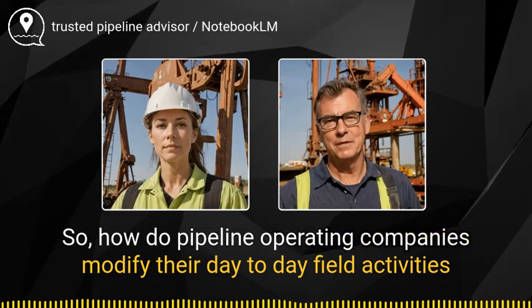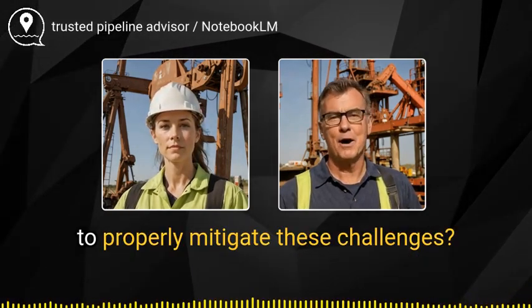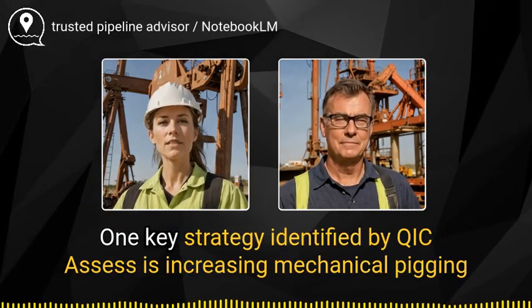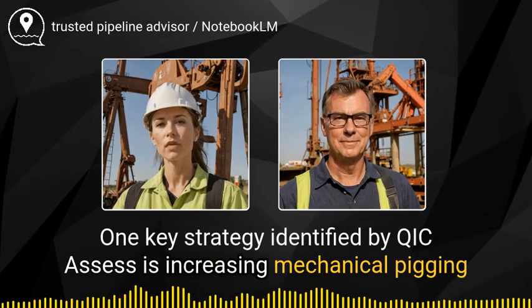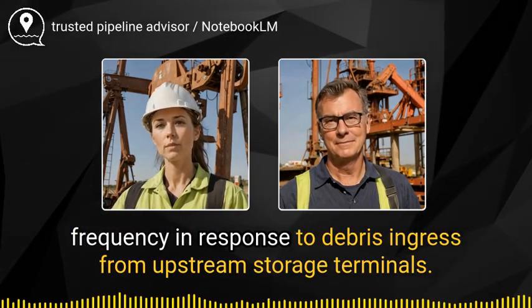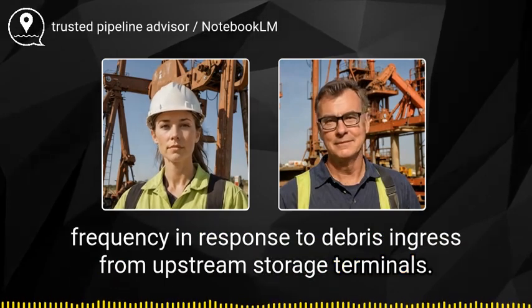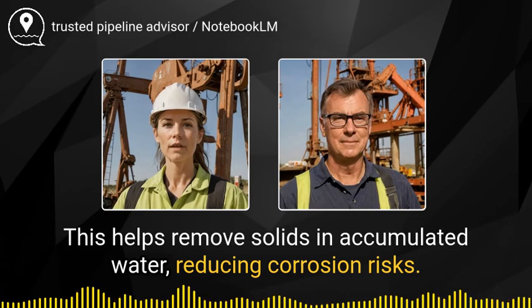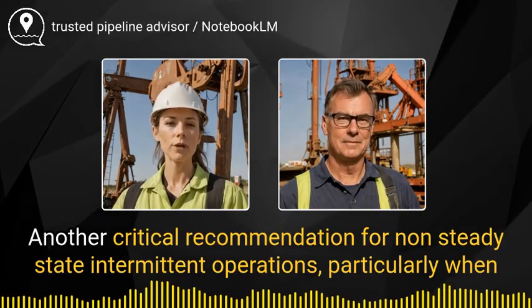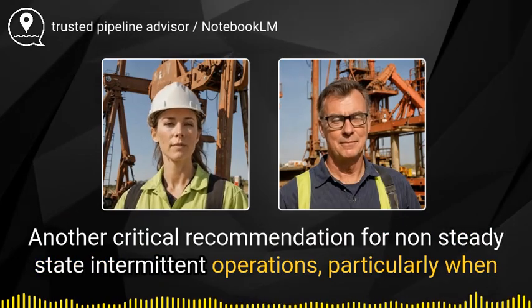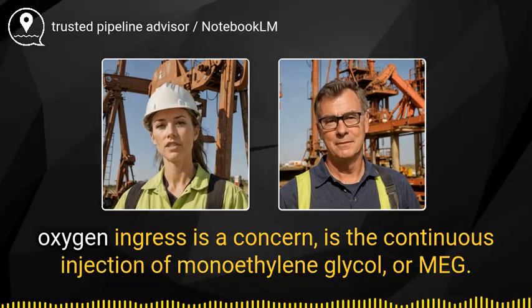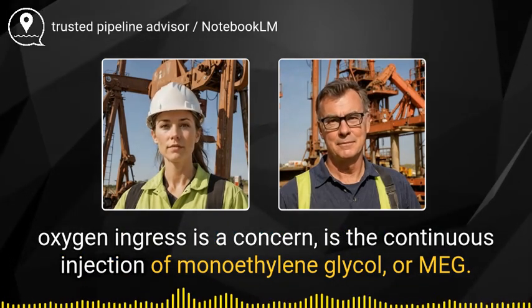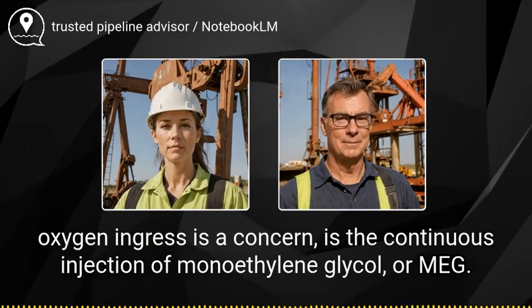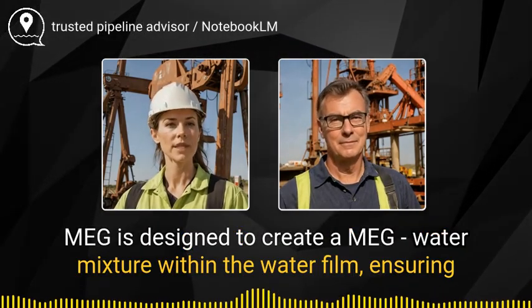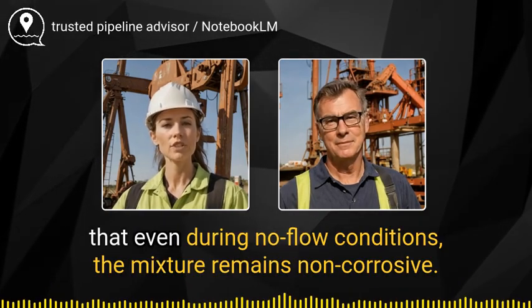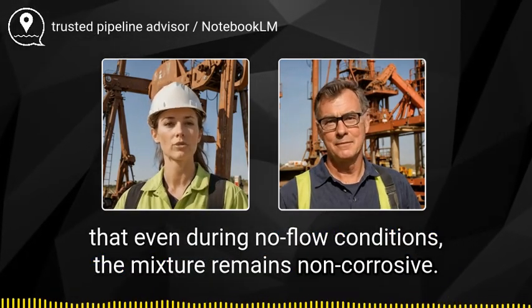So, how do pipeline operating companies modify their day-to-day field activities to properly mitigate these challenges? One key strategy identified by QIC Assess is increasing mechanical pigging frequency in response to debris ingress from upstream storage terminals. This helps remove solids in accumulated water, reducing corrosion risks. Another critical recommendation for non-steady-state intermittent operations, particularly when oxygen ingress is a concern, is the continuous injection of monoethylene glycol, or MEG. MEG is designed to create a MEG-water mixture within the water film, ensuring that even during no-flow conditions, the mixture remains non-corrosive.